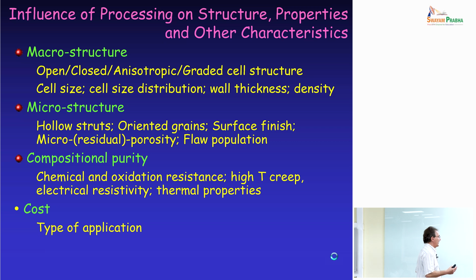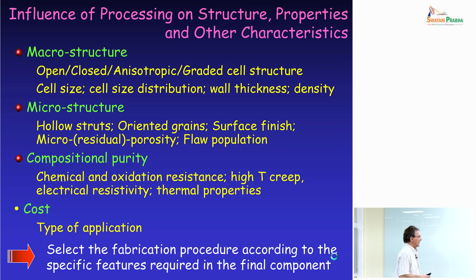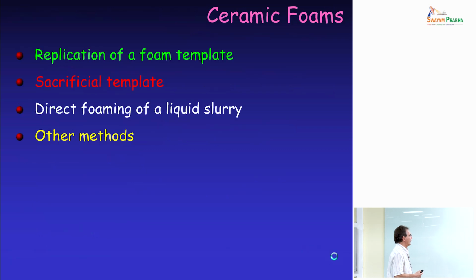You can have oriented grains, you can have different types of surface finish in your cellular material. You can have residual porosity, and certainly you have a certain flaw population that is important for controlling the properties in a ceramic material. Depending on the type of process, you can also have different types of compositional characteristics which affect different properties, including thermal properties, electrical resistivity, and so forth. And then, depending on the type of application, cost is also a driver for selecting the best procedure according to the specific features required in the final component.